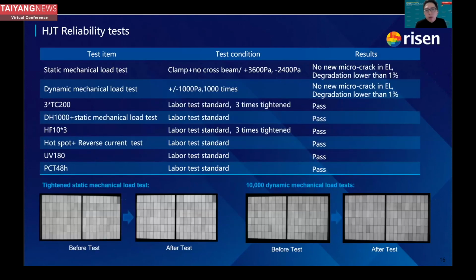And also to verify the reliability, after adopting our thinner wafer and low silver content paste, we did all kinds of tests: a mechanical test, dynamic load, thermal cycle test, damp heat test, humidity freezing test, hotspot test, and UV test, which is a big concern for others. After the tests, we found the reliability and performance of the modules still remain within the IEC standard. So it's feasible to adopt all these technologies.